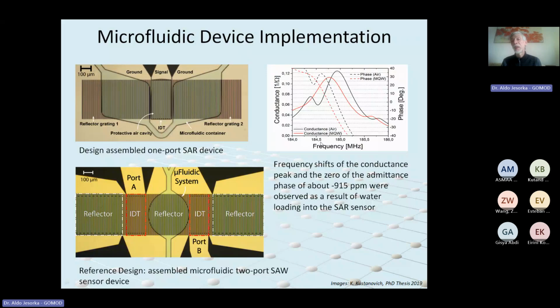Here on the right side, you see what is happening when you are looking at the resonance. Here in this case, 185 megahertz approximately. When you go from air, that is the black curve with a resonance frequency, to water, milli-Q water, which is the red curve, you see that there's a frequency shift, and nicely that also some of the extra resonances disappear here. In broken lines, you see that the phases of the signals, the zero crossing here of the phases, can also be used as an indicator of presence of molecules, change in viscosity, or similar.